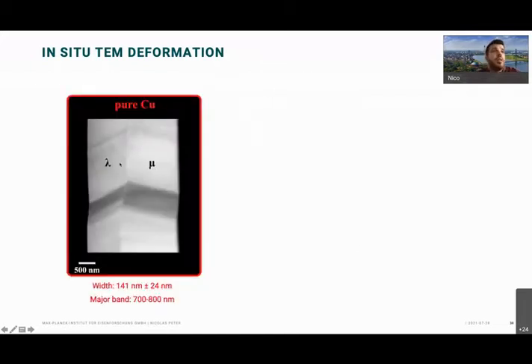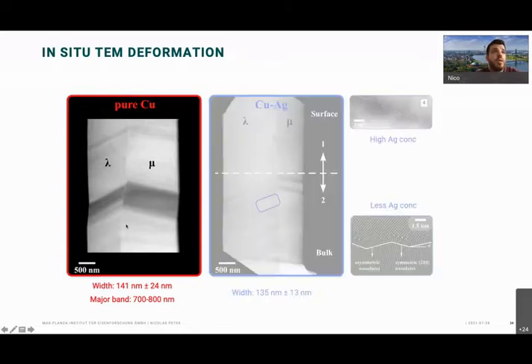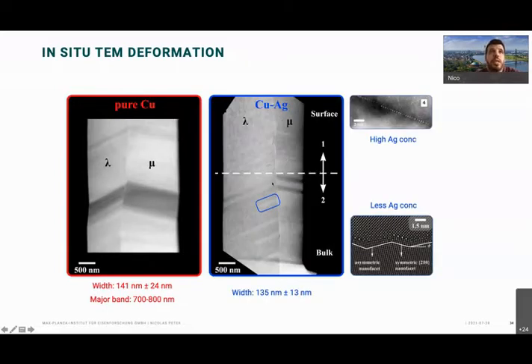So if we now take the sample and compare it to a copper silver sample, we see, well, we have a lot of these features now forming along the boundary until a certain point, and then we have nothing forming anymore. And this is up here the surface, and this is down here more towards the bulk. Also, we don't have this long extended features like on the left side. So we know from our experiments before that on the top towards the surface, we have high silver concentrations, and to the bottom, we have the less silver concentration, the nanofacet case. So apparently, the 3 states that we have differ in what happens under deformation conditions.